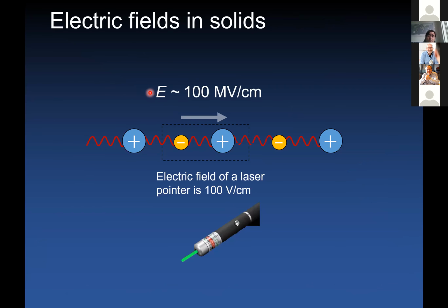And in order to perform these experiments effectively, you need to ask yourself, what kind of electric fields do I need? And in a solid, you typically have electric fields of the order of hundreds of megavolt per centimeter. So these are the typical interatomic electric fields. And in a simple laser pointer, you have electric fields of the order of 100 volt per centimeter. So a laser pointer will not do much, even if it's tuned to a particular resonance, it will not cause particular atomic displacements. So you want to generate electric fields of this order of magnitude.